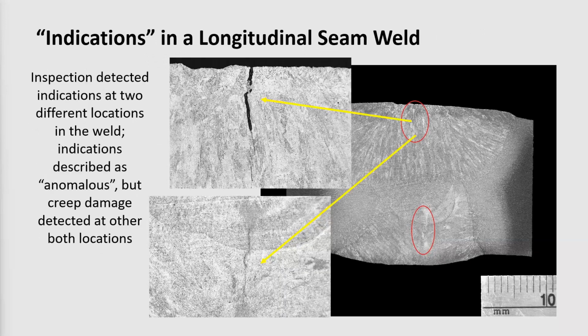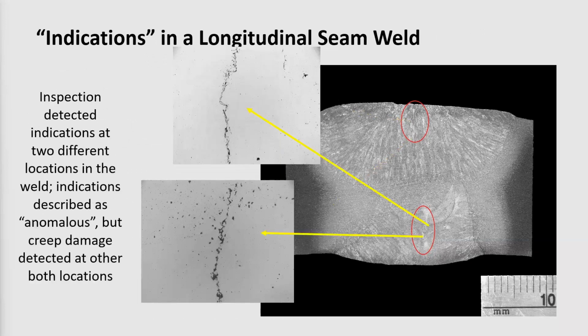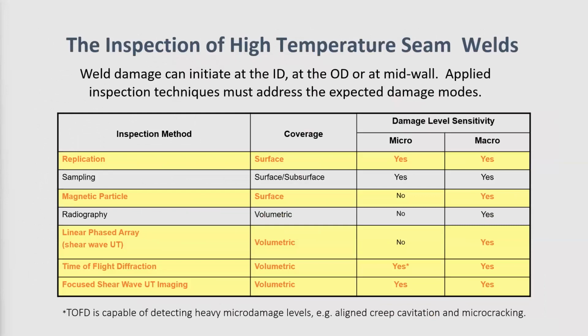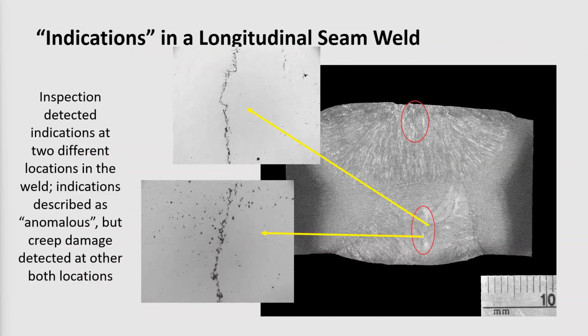And again, another example of indications that were found in the weld. When they were examined, it was confirmed that this was creep damage, but there was damage at other locations that was not detected by the ultrasonics being used, simply because it was below the threshold of detectability for that technique.